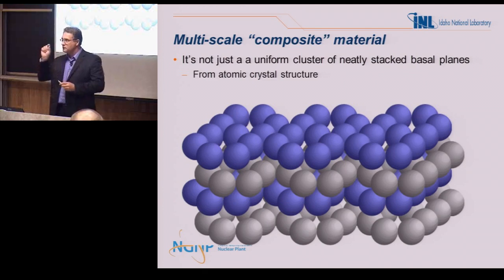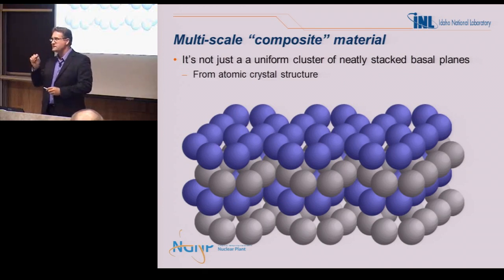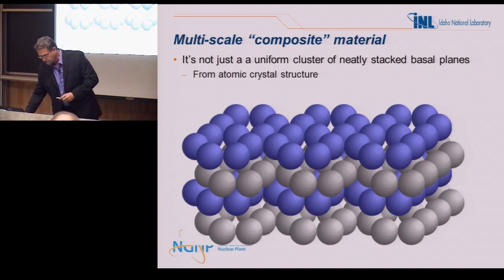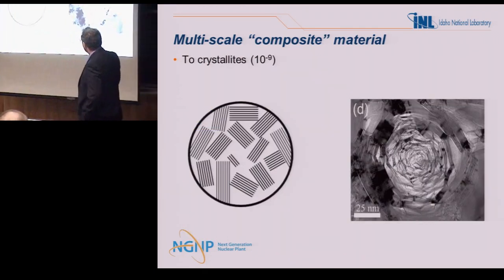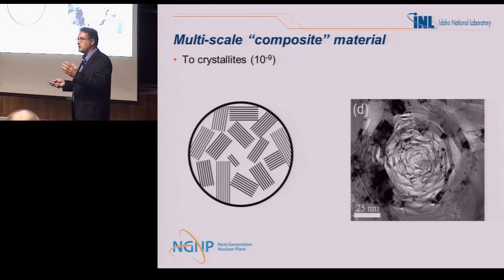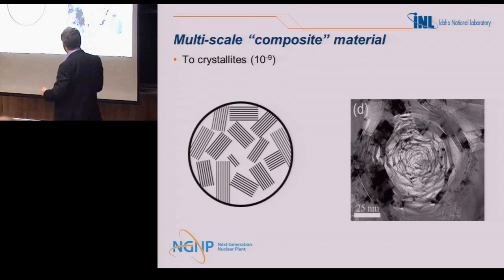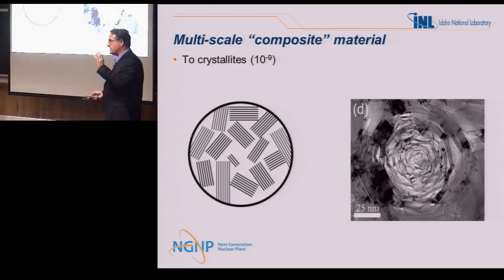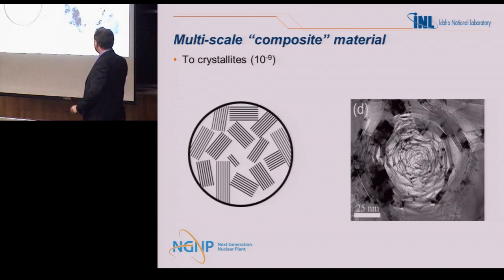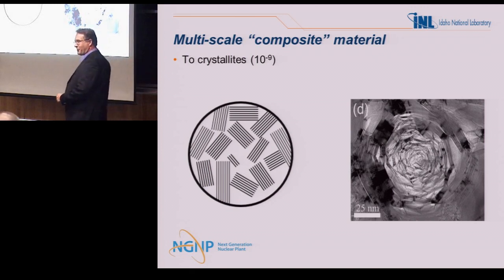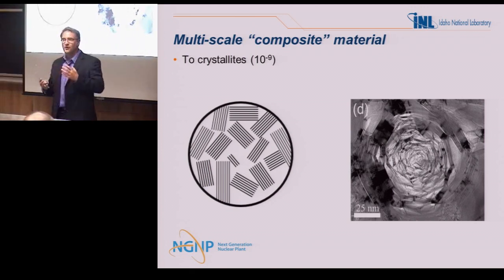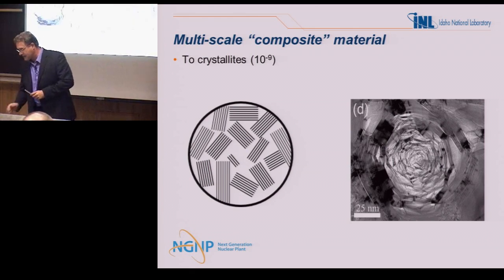It's a composite of these things, and the smallest pieces of that are made up of these anisotropic crystal structures. All right. These crystallites, you're talking about nanometers at this point, where the crystallites and the forming up of the graphene planes and stacking them up. This is my language challenge for the day. This is a quinoline insoluble particle, which is the benzene-rich precursor material for forming those hexagonal planes, all right? So that's what that is.